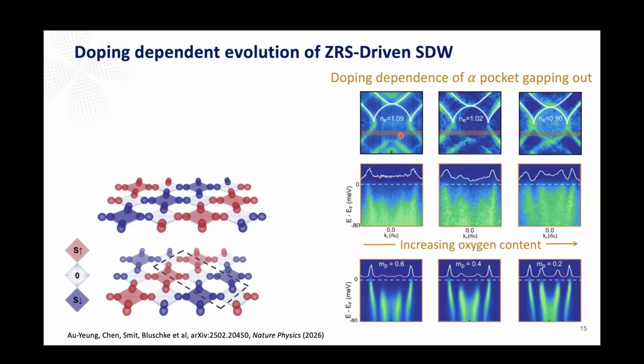I mean, this is beautiful, but I wouldn't necessarily imply that the driving force for the order is the Fermi surface nesting, because basically any mechanism that leads to that order with that wave vector will open up gap-like features. I fully agree with you. In fact, I make this point even more strongly. If you look at the charge order in cuprates, you extract the same relation between the charge order and the Q vectors in the fermiology. But sure enough, I wouldn't believe that to be due to nesting. Okay, but certainly it's beautiful. Thank you.